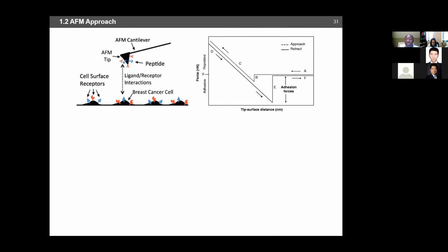And to study these, we've done adhesion studies where we coat the tip of the AFM with the peptide or protein that we're trying to study as a molecular recognition unit. And we check to see what the adhesive interactions are between the tip and the cells. And so when you do this, you do a force microscopy experiment where you bring the tip in contact with the tissue, it jumps to contact.